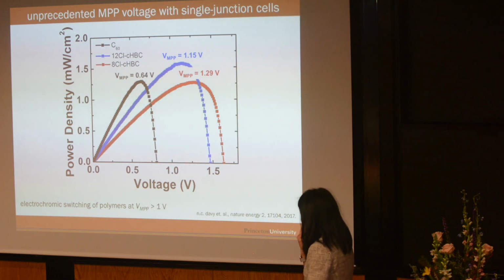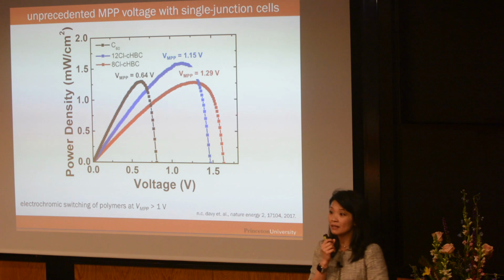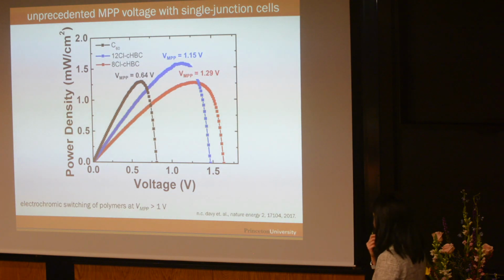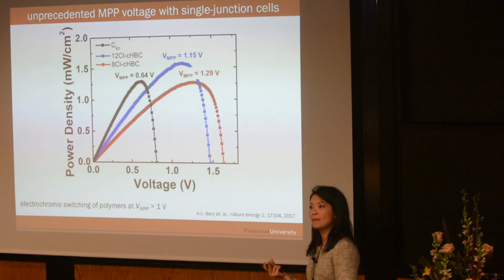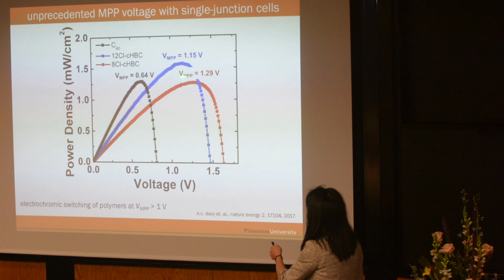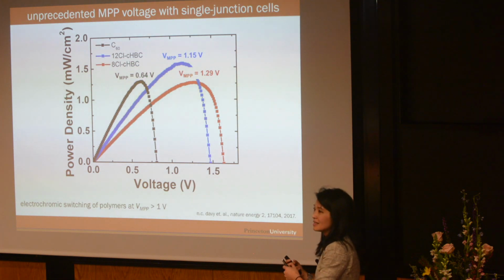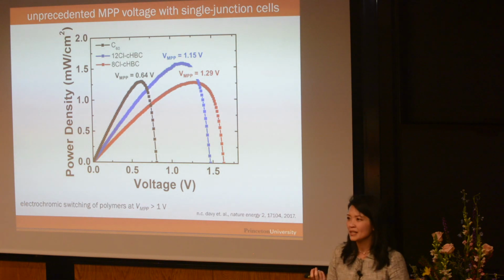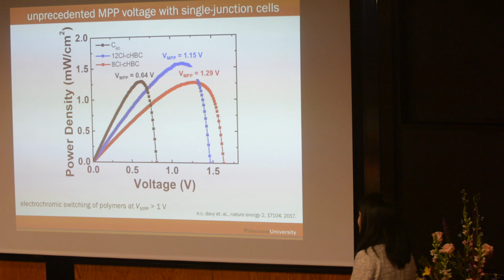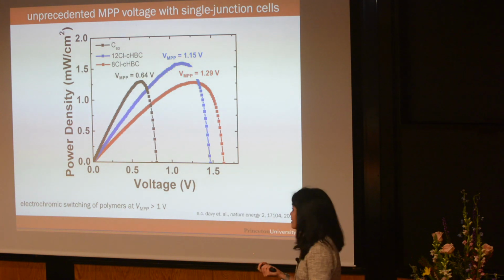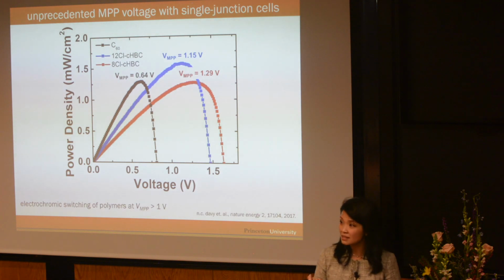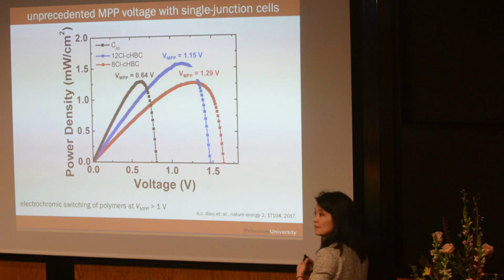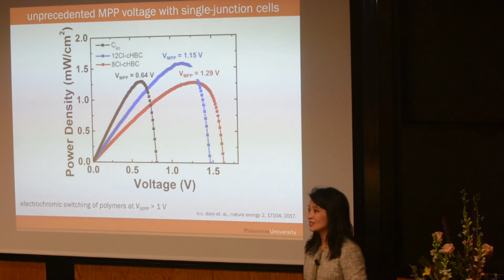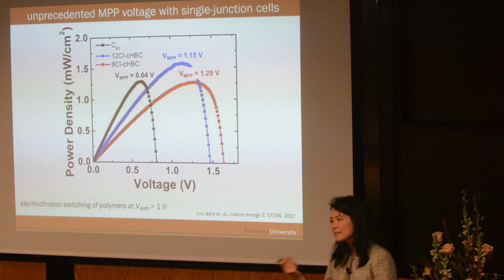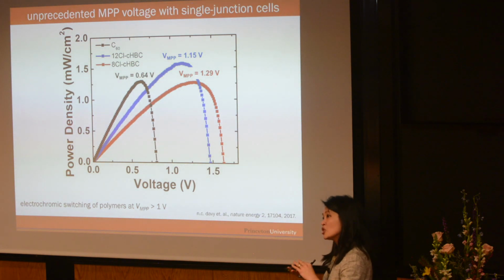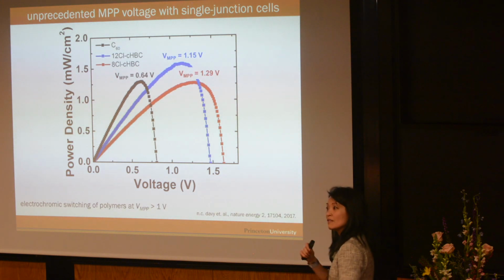Another way to quantify the performance of our cell is to look at the power density. And so this is basically taking the voltage of our solar cell, multiplying it by the short circuit current density. This is useful because it tells us the quality of the power that we're getting out. So you can look across these three devices with C60, with 12Cl, with 8Cl. The power densities are comparable at about 1.5 milliwatts per centimeter squared. What's different is the working voltage that you get out of these devices. With C60, the working voltage is only about 0.6, but with our cells, we get about 1.2, 1.1, and that's significant because now that you have these high voltages and the switching for electrochromic materials is about 1 volt, we can now make a single, simple junction cell and use it directly to drive the switching of the electrochromic window.